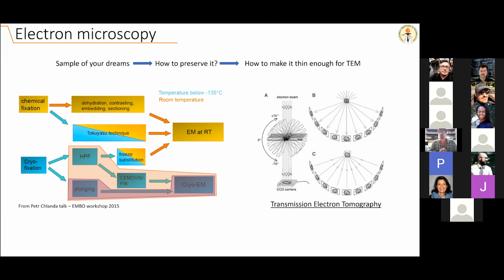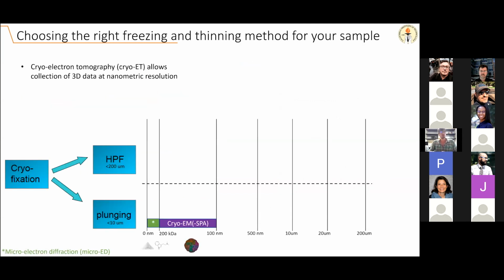We'll be talking a lot about transmission electron tomography, so I just want to have a very quick word on it. So what exactly does tomography entail? It means that we have our specimen here in panel A, where it says ice, and this specimen is tilted at various degrees, and at each of these tilt angles, we acquire a 2D projection. And then with the collection of these 2D projections, we can come back to the 3D volume. So cryo-electron tomography allows to reconstruct the 3D volumes of our specimen of interest.